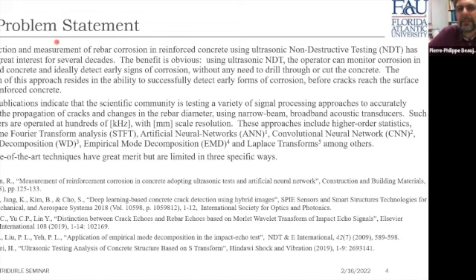But here, what we intend to do is not mitigate this corrosion effect, but detect and identify it early. And there comes my field of specialty, which is underwater and high frequency acoustics. The idea is this: the detection and measurement of rebar corrosion in reinforced concrete using ultrasonic non-destructive testing, usually labeled NDT, has been of great interest for several decades. The benefit is obvious. Using ultrasonic NDT, the operator can monitor corrosion in reinforced concrete and ideally detect early signs of corrosion without any need to drill through or cut the concrete, which is a costly process and quite often highly impractical. The limitation of this approach resides in the ability to successfully detect early forms of corrosion before cracks reach the surface of the reinforced concrete.